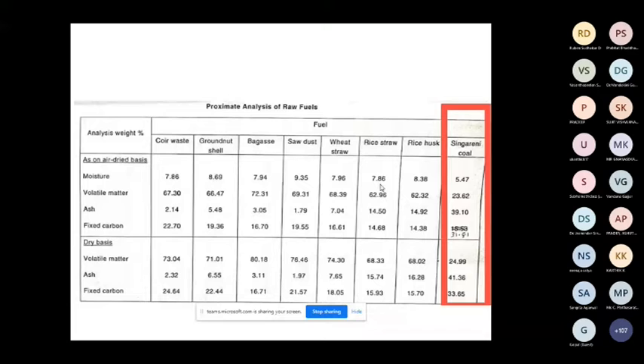Only the straw fuels, rice straw at 14.5% and rice husk at 14.9%, are high. Then wheat straw is 7%. All other things are around 2 to 3%, less than 2%. With respect to ash content, biomass is a much better fuel compared to coal. Coal, average Singareni coal, has 39% ash content, whereas biomass ash ranges from 1% to a maximum of 14 to 15%. Fixed carbon is more or less the same: 22%, 19, 16. Coal has 31%. So that is the proximate analysis of biomass fuels.